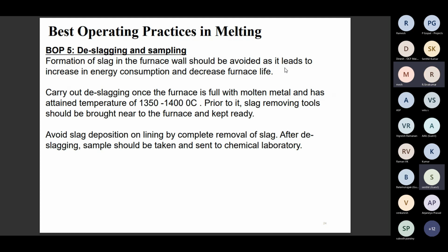Deslagging and sampling. Formation of slag on the furnace wall should be avoided as it leads to an increase in energy consumption and decreases the furnace's life. Carry out deslagging once the furnace is full with molten metal and has attained a temperature of up to 1400 degrees. Prior to slag removal, tools should be brought near the furnace and kept ready. Avoid slag deposition on the lining by complete removal of slag. After deslagging, samples should be taken and sent to the chemical laboratory. So deslagging and sampling is very, very important.